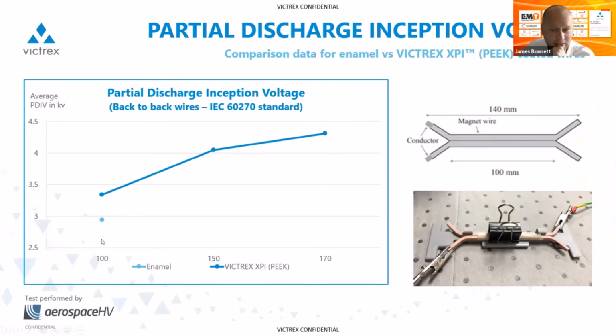And you can see from the test data we measured, for the same thickness of coating materials, we have enamel down here in the light blue, and the XPI coating in the dark blue, there's about a 10% improvement for a given thickness. We were unable to find any commercially available enamel coatings with thicker thicknesses, but at least on this graph you can see how the relationship with PDIV changes with increase in thickness.